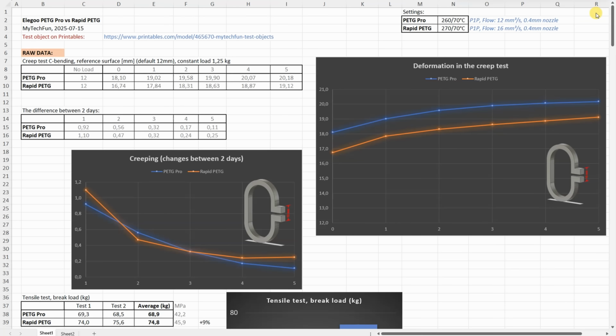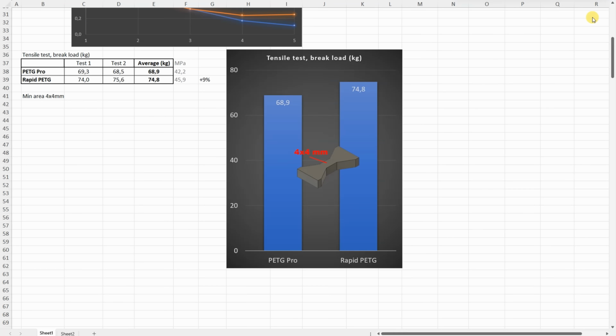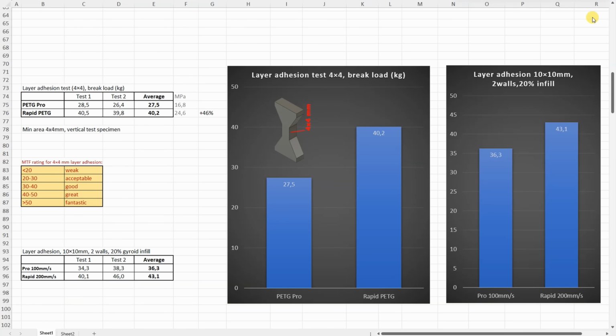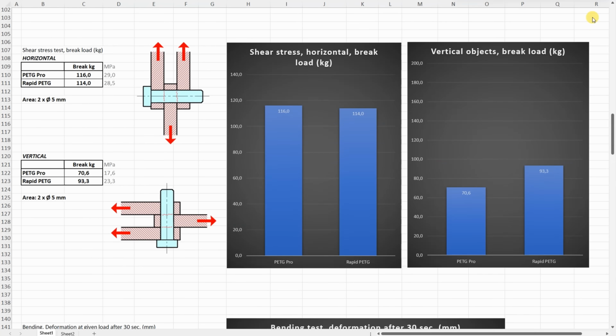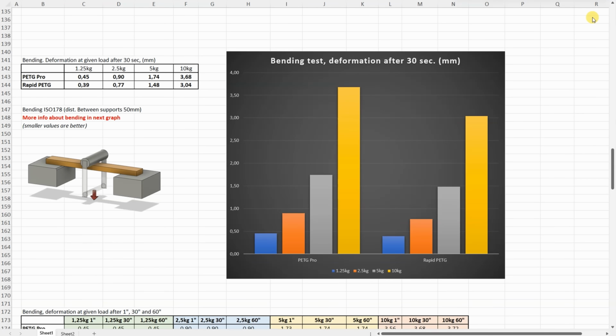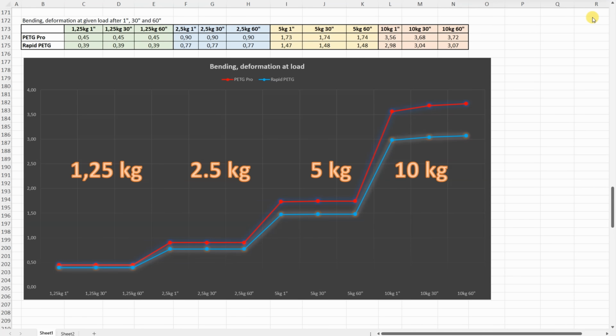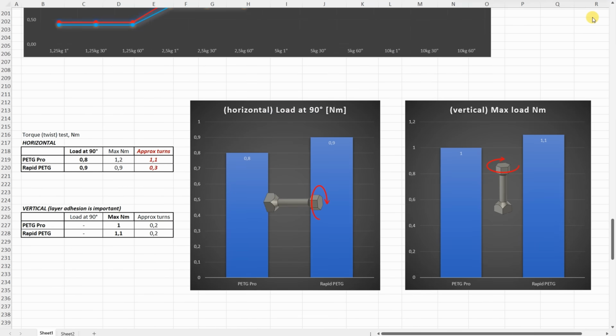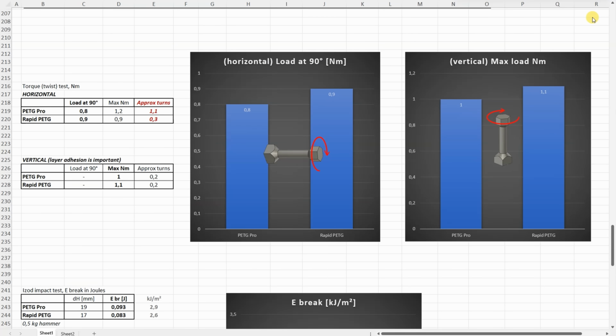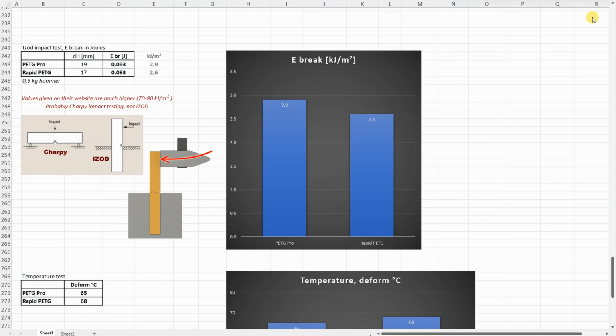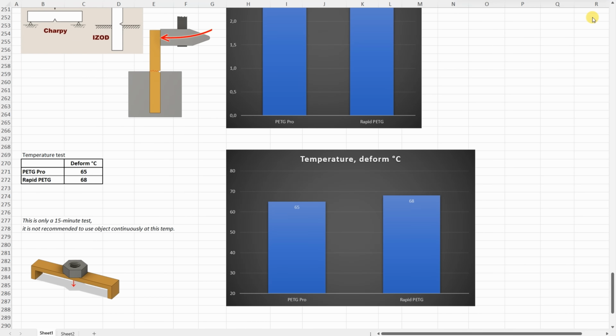All results one more time without any additional comments, and these 2 lines will be added to the summary table for my Patreon supporters. Results for the layer adhesion test, shear test, bending test, deformation after 30 seconds, bending test, deformation after 1, 30 and 60 seconds, torsion test, impact test, and the temperature test.